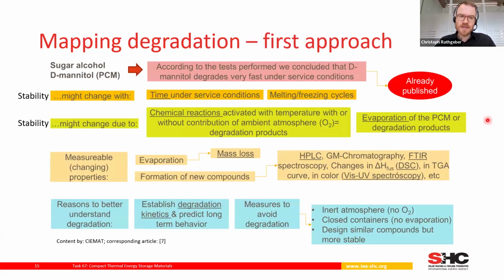Here you see an example for a sugar alcohol used as PCM, studied by CIEMAT. They built in their expertise on the degradation, or the stability testing, of this sugar alcohol, with a conclusion on the overall stability of the material, then on the effects that influence stability. So stability might change, as you see here, with the time under service conditions, so time under high temperature, melting-freezing cycles. Then they said that stability might change due to basically two processes, chemical reactions or evaporation.